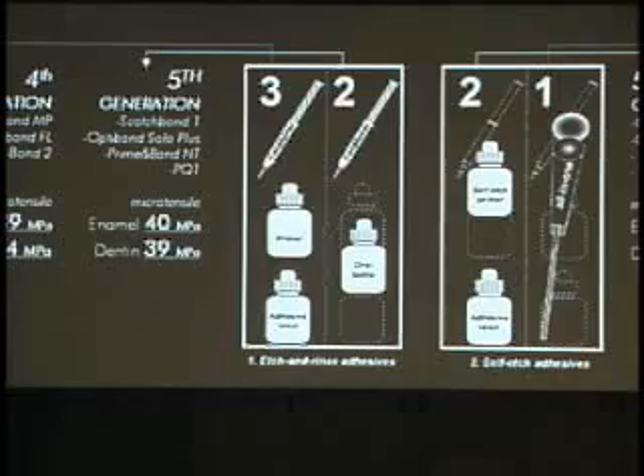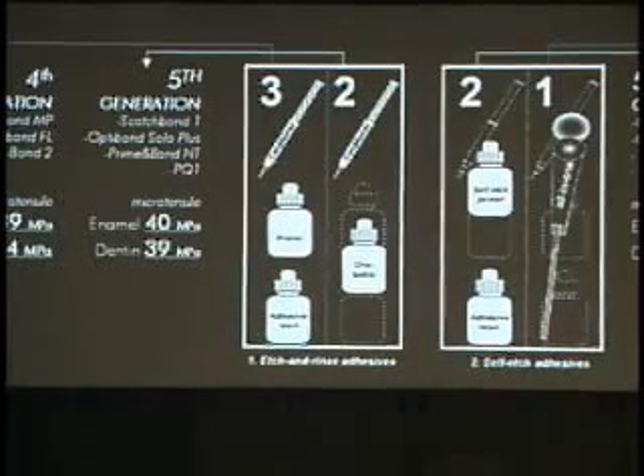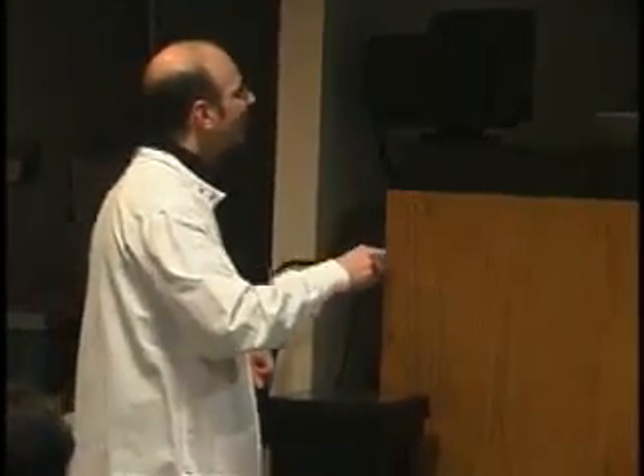And just to make a summary of dentin bonding, don't believe that the latest generation of bonding agents are better. Actually, the standard is still the 4th generation adhesive, which are the only ones that give consistent and stable bond strength to enamel and dentin. I want to show you an example of these old 4th generation products, OptiBond FL, which is almost a 15-year-old product, and is still a golden standard today in bond testing. So it's a 4th generation 3-step etch and rinse adhesive.